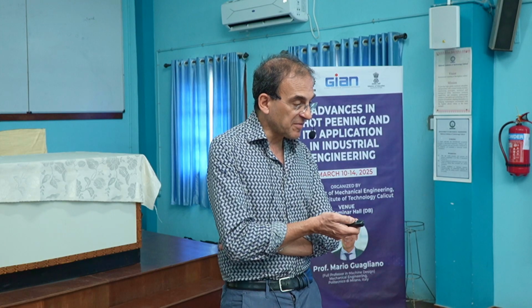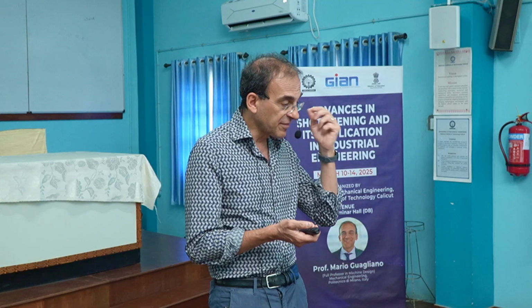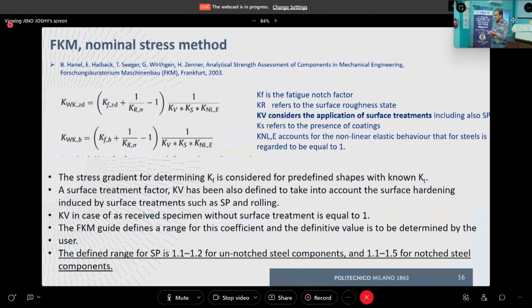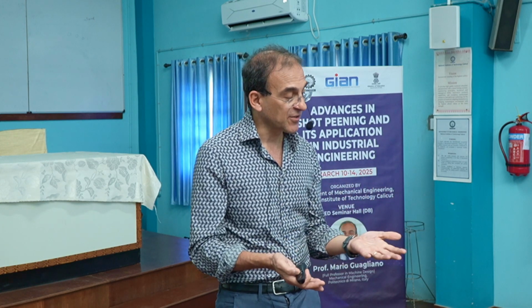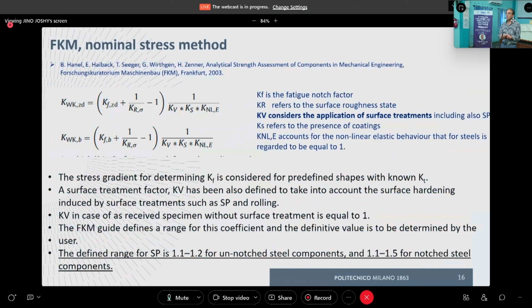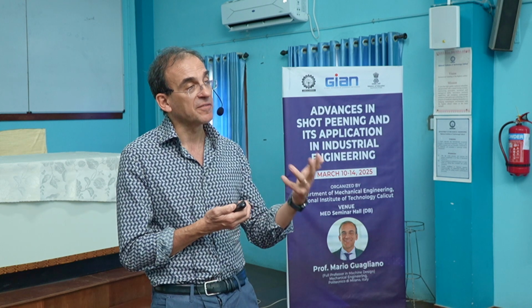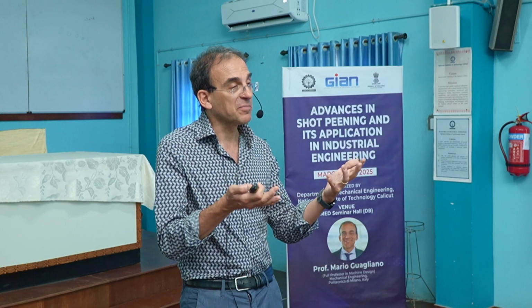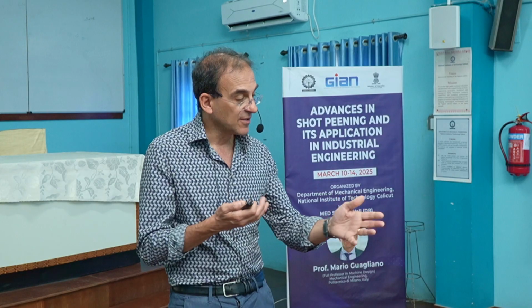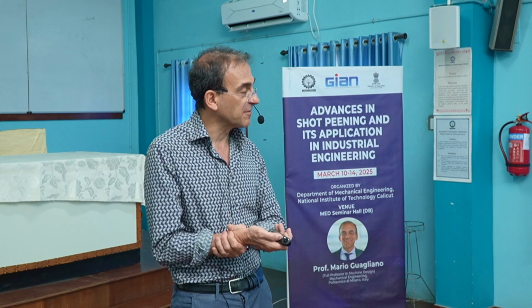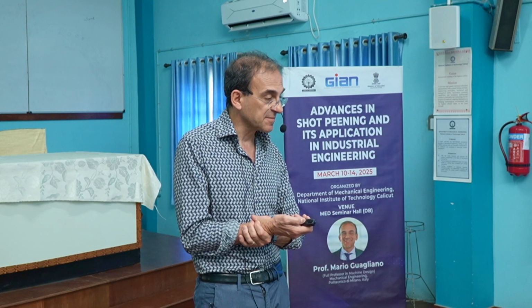KV is the surface factor, defined also for shot peening and deep rolling. If we have not done any treatment, surface KV is equal to 1. And if we focus on shot peening, let's see that FKM considers shot peening in a more appropriate way. That is to say, if we are considering a smooth sample, the positive effect of shot peening is in the order of 10, 20%, 1.1, 1.2. If we are considering a notched steel component, the effect is larger, from 10% even to 50%, 1.5. And it's up to our expertise about shot peening and the way we have designed the treatment to apply 1.1, 1.2, 1.3, or even 1.5. And of course, it depends on the quality control we are using.